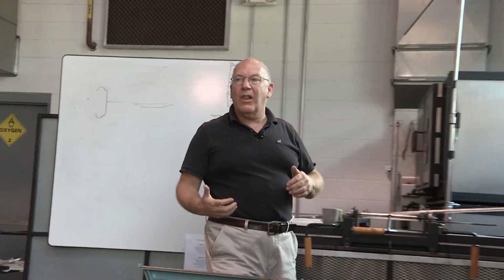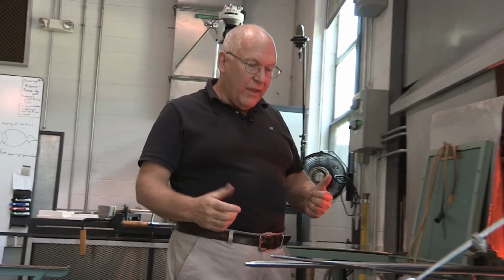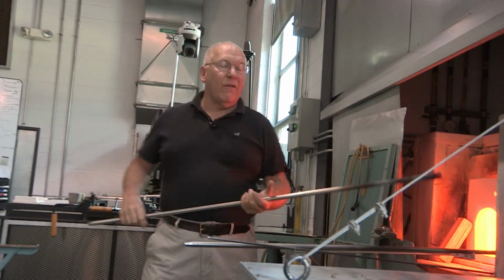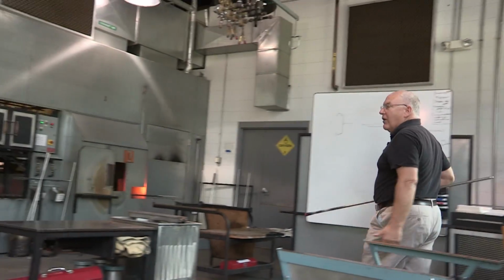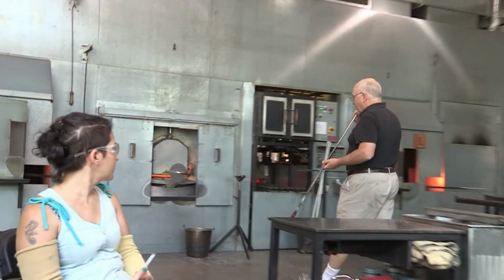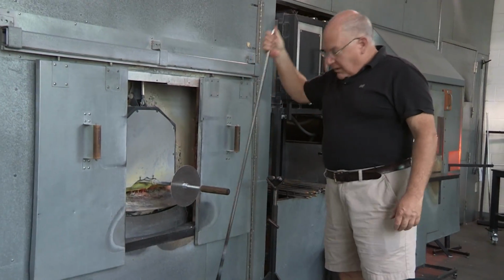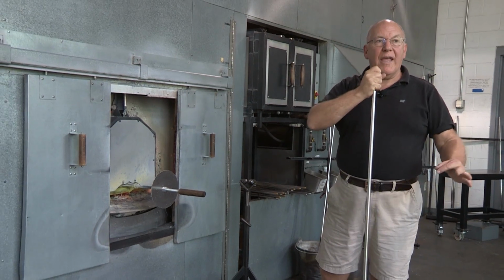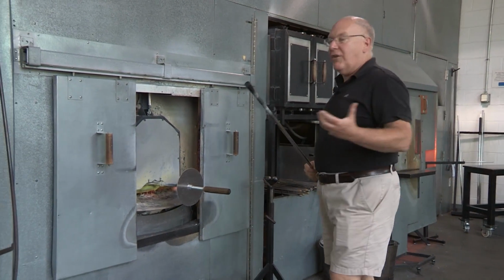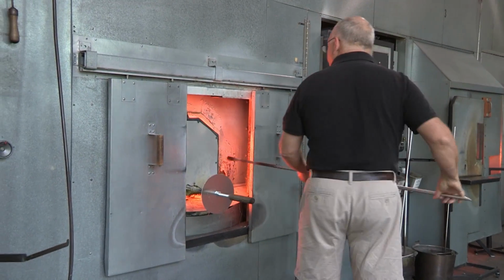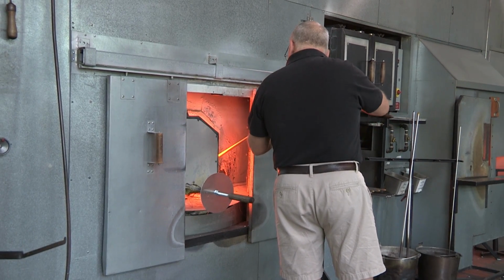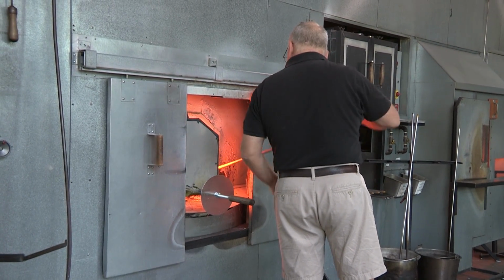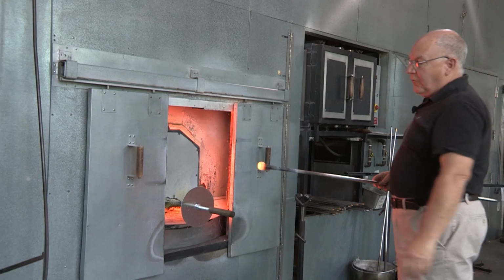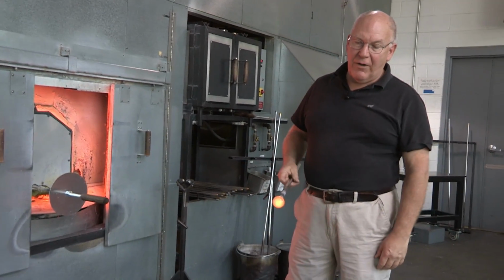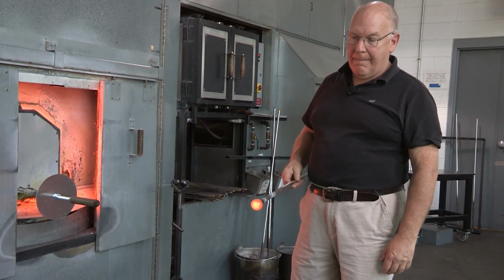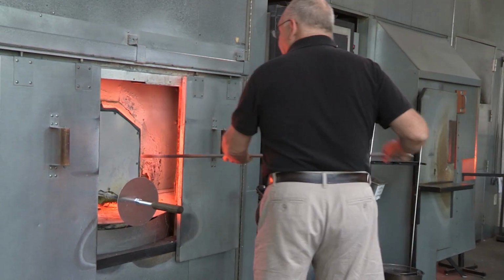I'm just going to gather clear glass, set it up, and do it real quickly so you see it without the canes. I'm going to gather from the big furnace, and I'm going to use the coating gather and collecting gather process to get as much glass as I can really quickly. Here's my coating gather. I'm going to let that stiffen up a little bit. Here's the collecting gather.